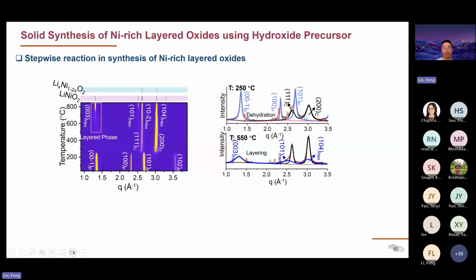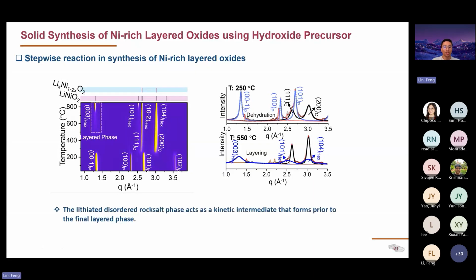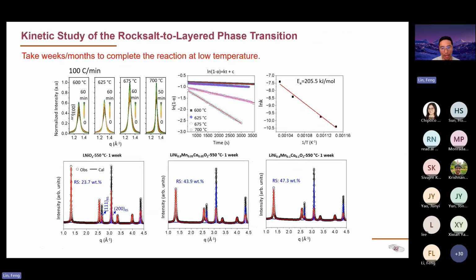So this is a phase step, with further analysis of different phases that are present at different temperatures. There's a layering that's happening above 550. You start to see this buildup of the 003 peak belonging to the layered phase. So if you look at the kinetics at low temperature following the traditional pathway, the pathway that people are taking, the calcination actually starts from the layered metal hydroxide to a rock salt phase, and then to the layered phase eventually. The rock salt phase is very stable. It's not easy to convert to the layered phase because cation ordering will take a lot of energy.